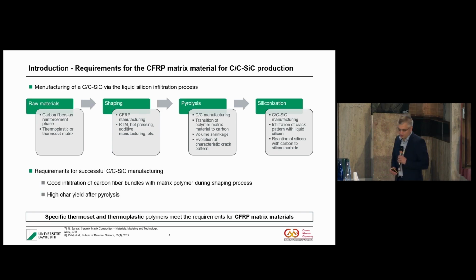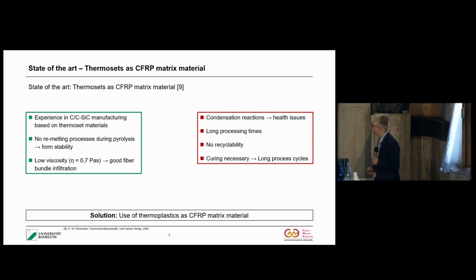And one aspect which is always important if you have different polymers is that you have to ensure good infiltration of the carbon fiber bundles in order to protect the carbon fibers during siliconization, and also to have a good load transfer later on. And the polymers have to have a high char yield, which is also not so easy to realize. Often these polymers which have a high char yield have quite a high viscosity, so that means the processing is quite complicated.